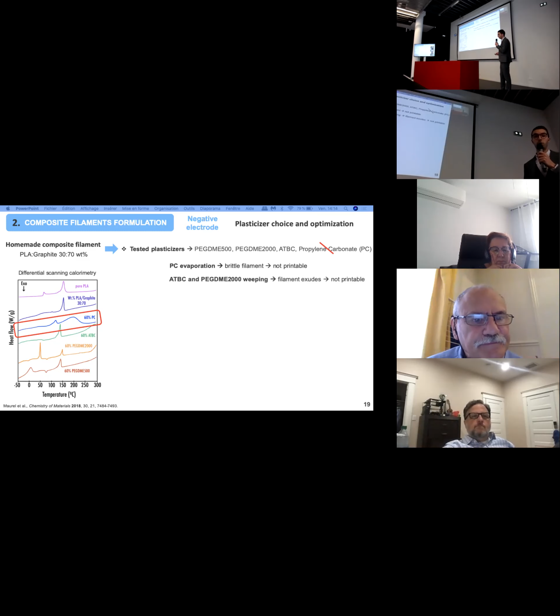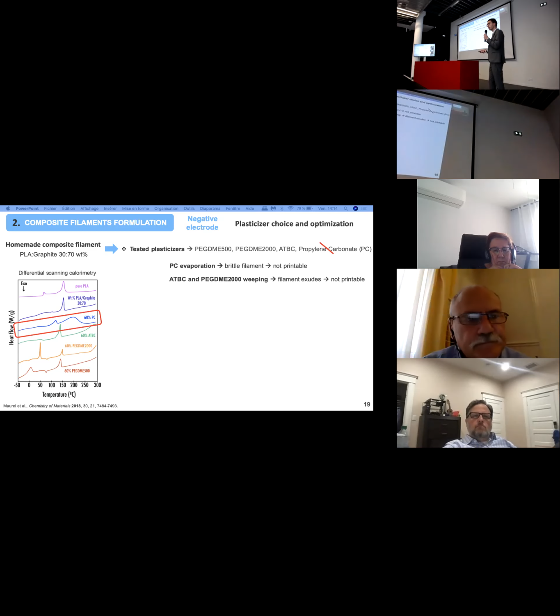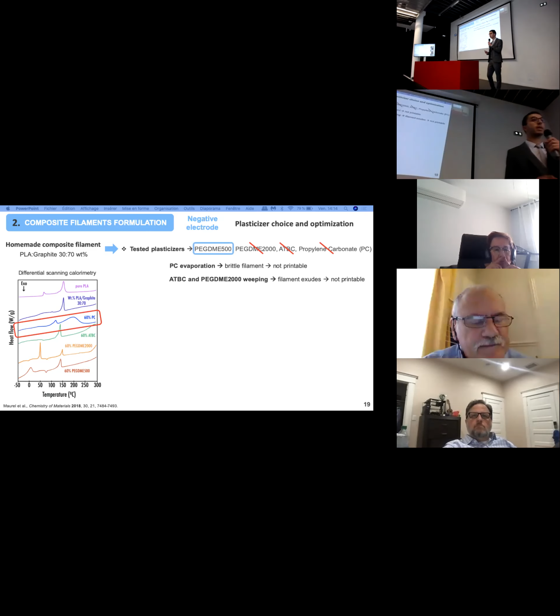Then we tried to make a filament with ATBC and PEG-DME 2000. But unfortunately, after only a few days, the filament was really, really brittle. And we saw some tiny drops on top of these filaments. Both plasticizers were exiting the filament, meaning that maybe there was an incompatibility between the plasticizer and the PLA polymer matrix here. So again, we ruled out both plasticizers from this process. And finally, with PEG-DME 500, we didn't have any issue here.